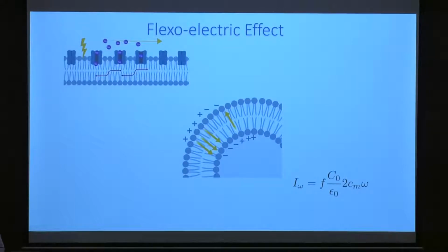As for the flexoelectric effect, the membrane is actually a curved structure, not a flat structure. And there are currents and voltages induced all the time and changing, which causes the membrane to fluctuate and move in a very organized manner, which causes oscillations. These oscillations induce flexoelectric currents in the membrane, modeled using this equation that depends on the capacitance, the maximum curvature, the oscillation frequency, and the flexoelectric constant.